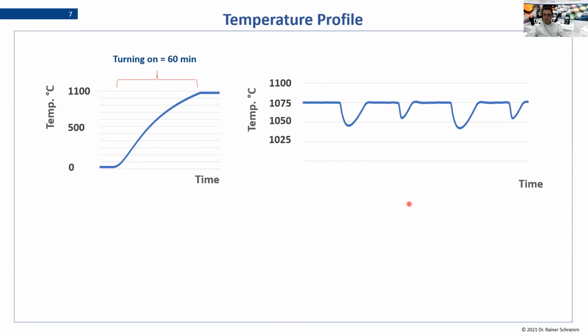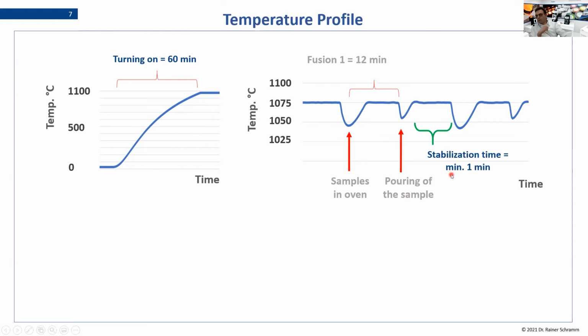In a routine fusion process now, and I come back to my cement example, we would start by introducing 4 crucibles at once into the furnace. We would fuse for about 12 minutes. We will pour our 4 samples, and then, important, there comes a stabilization time. That means how long does the furnace need to come to the same conditions as before the first fusion? So that when we repeat our fusion for 4 samples, we get exactly the same beads afterwards as in the first run. And this stabilization time you can program.